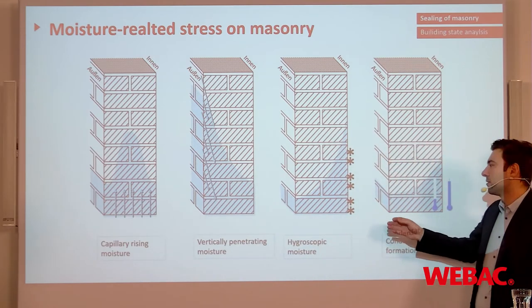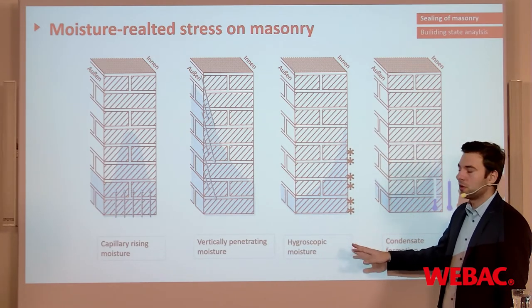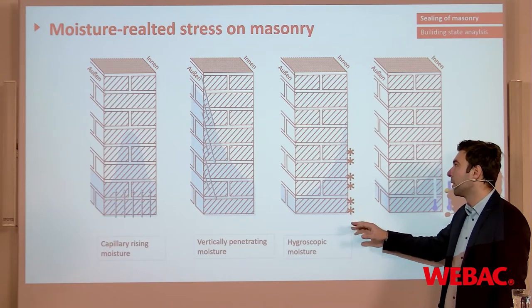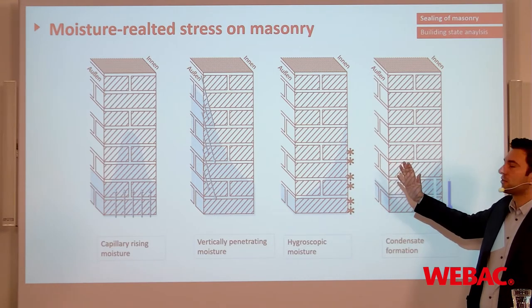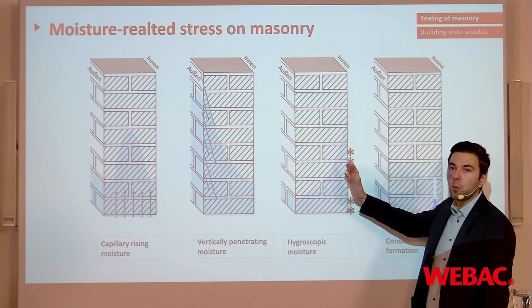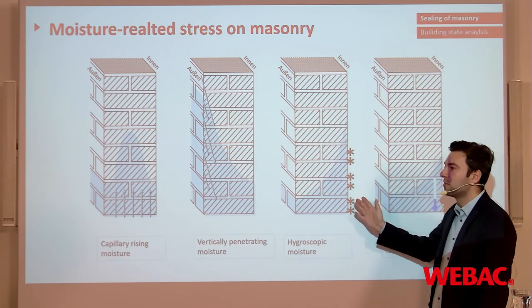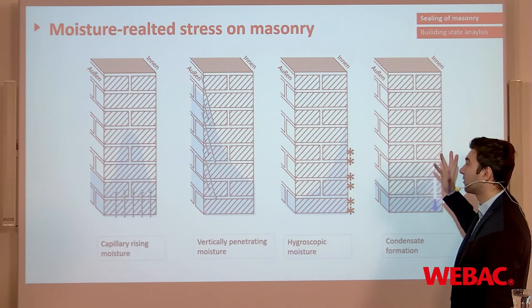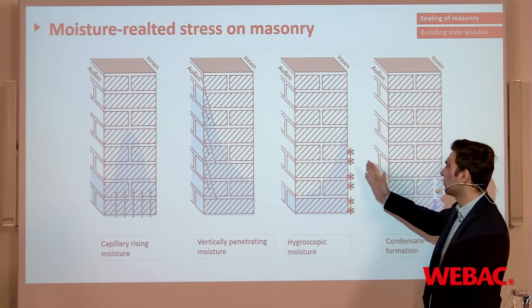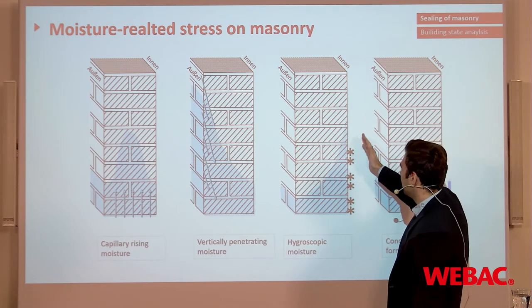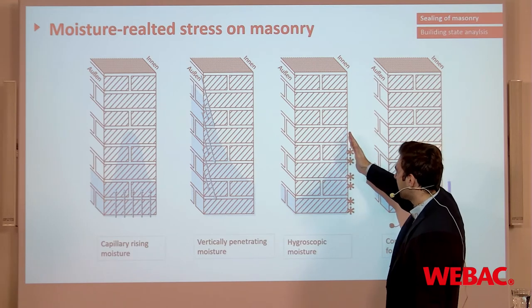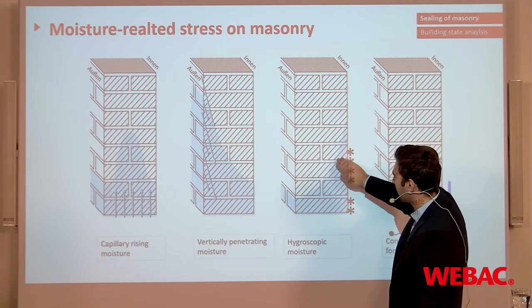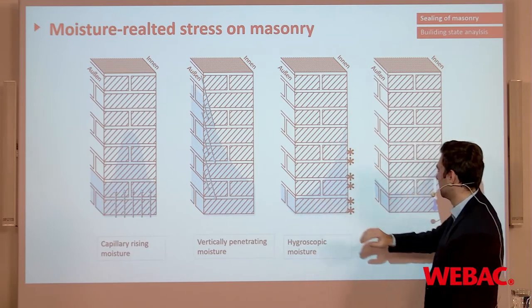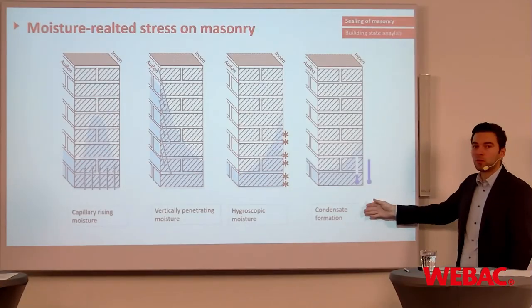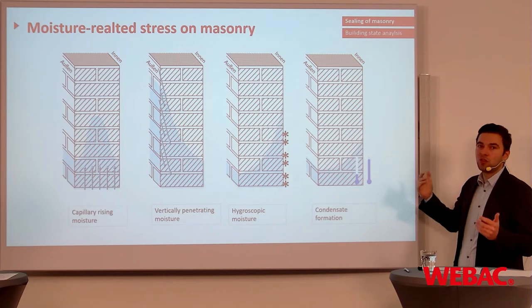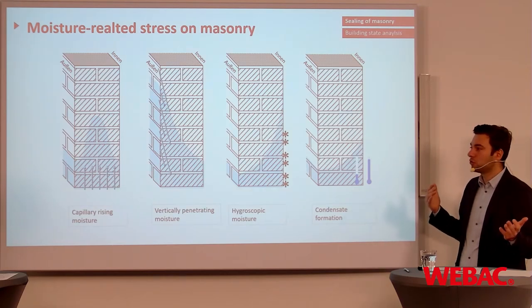The other thing, and this is something that is common in older structures, is hygroscopic moisture, meaning you have salts that are sticking to the inside of your wall. These salts are hygroscopic, so they are going to suck the water into this construction, and you see that the moisture is going from the inside in a higher degree and is getting less to the outside. Last but not least, maybe you have condensate because of changes in heat and cold temperatures.